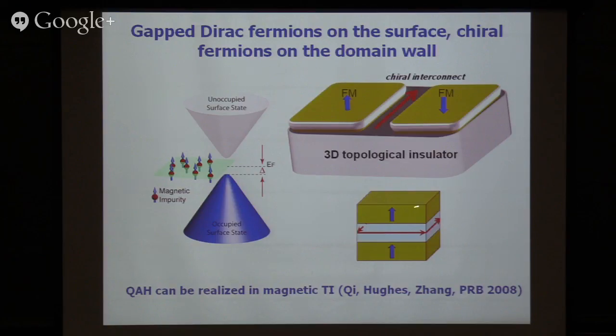So imagine that I put the top surface and bottom surface with magnetization. They will all open up a gap. But on the top surface, the direction of magnetization is parallel to the surface normal, while on the bottom surface, it will be anti-parallel to the surface normal. So in that sense, it makes the four side walls look like a domain wall like this. And that will have a chiral current. So without an external magnetic field, without any Landau levels, in this magnetically doped topological insulator, you can actually have this chiral edge state, which is now only flowing in one direction, and the sense of direction is selected by the direction of the magnetization.